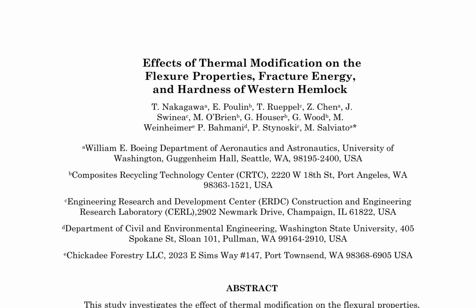Despite such advantageous tendencies, brittle attributes escalated sharply among the modified specimens upon testing of fractures, inducing decreased fracture energies significantly.